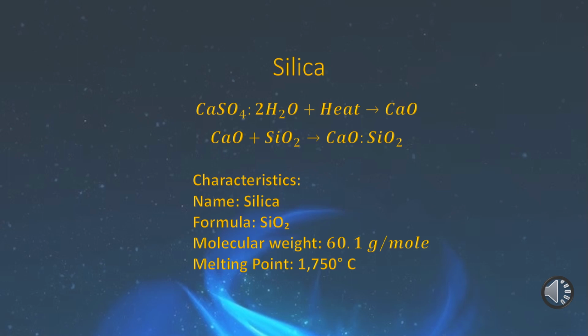Silica is the strongest acidic flux used. When subjected to high temperature and it starts to melt, it readily combines with the metal oxides to form silicates. This is actually the foundation of all slag material. Calcium sulfate, when heated, eventually breaks down and forms calcium oxide. Limestone is calcium carbonate. It too breaks down to form calcium oxide. The two dots in the formula simply mean that this is a fused silicate of calcium oxide and silicon dioxide.